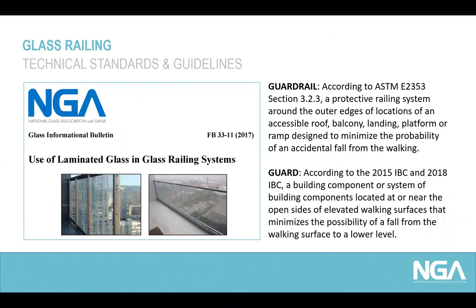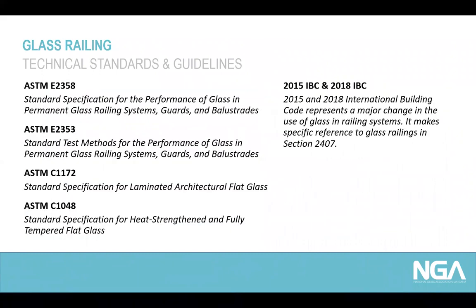NGA issued one GIB summarizing important rules for use of laminated safety glass in glass railing systems. So both ASTM and IBC define guards and guard rails basically as protective railing systems close to openings or outer edges to minimize risk of accidental fall to lower levels of a building. There are some rules which have to be taken into account working with glass railings, and there is first of all ASTM E2358 as a specification standard for glass railings. There is ASTM E2353 as a test standard, the test method standard for glass railings.